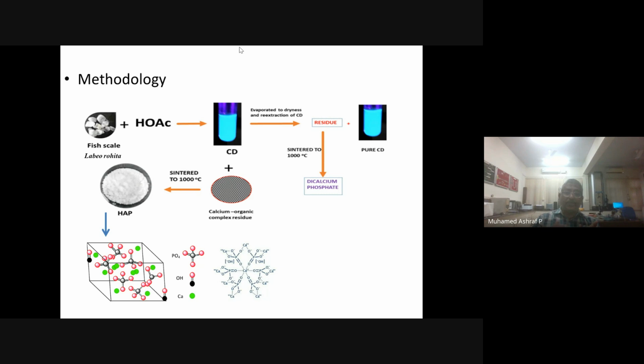So that precipitate we have filtered out, and then we have sintered it to 1000 degrees centigrade, and we have got a white hydroxyapatite. This hydroxyapatite my colleague also prepared. It is a highly nano-sized particle. That is the advantage. Earlier, we were talking about hydroxyapatite which generally comes with a larger particle size. Here we are getting very fine nano-sized hydroxyapatite, and it is white in color.